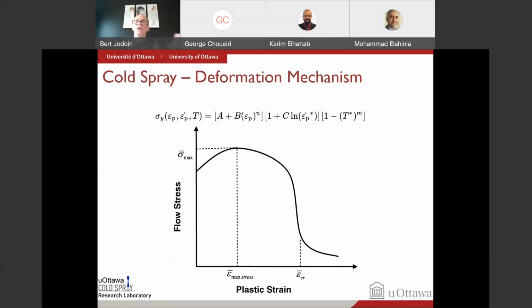So when we look at one particle, what happens is when it impacts the substrate, it's going to start to deform, but we deform it so quickly that locally most of this energy is transferred into heat, and you're going to heat the material very, very locally, and now it's going to start to behave like a liquid. So you're going to get what we call the adiabatic shear instability.